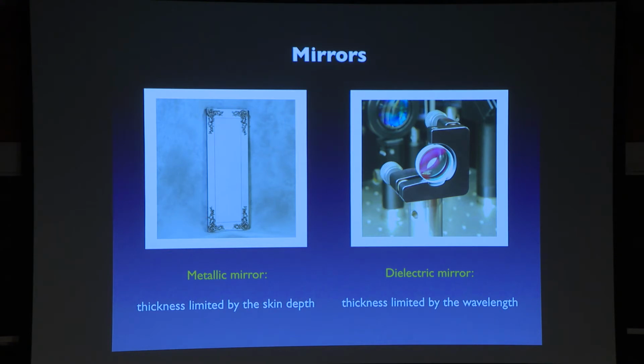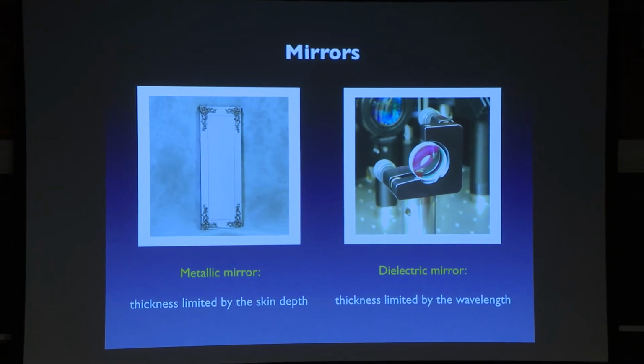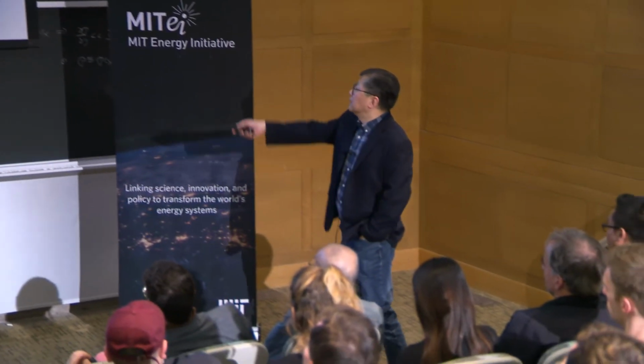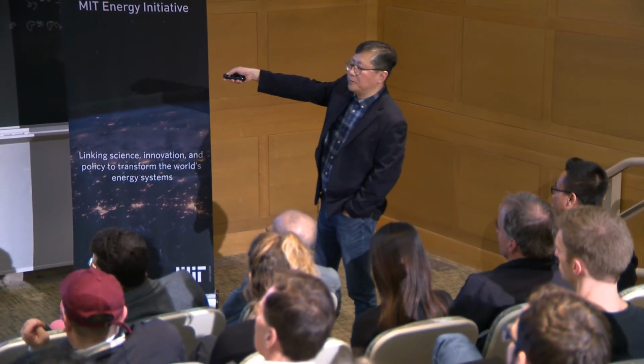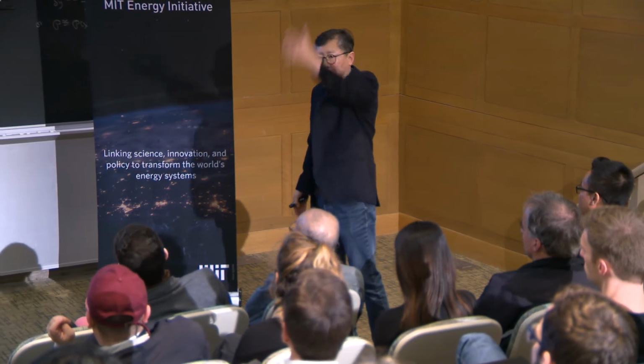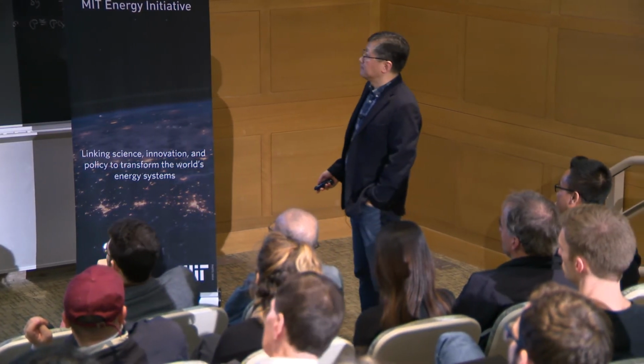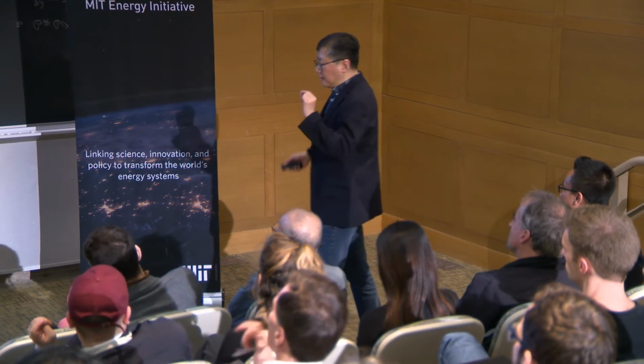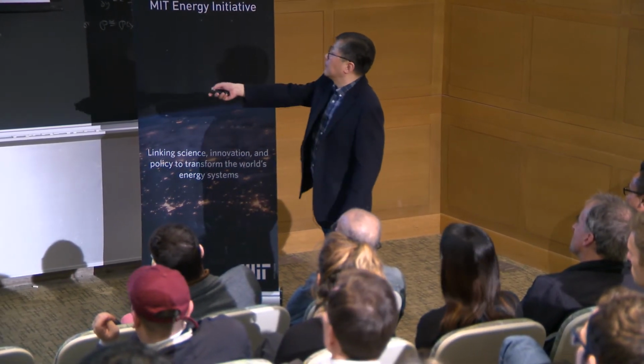So mirrors are ubiquitous everywhere. One of the things about mirrors that you often do not think about is the fact that mirrors should actually have finite thickness. Depending on the mechanism that you use to realize a mirror, whether it's a metallic mirror or a dielectric mirror, you actually have to have something like a micron thickness to get the proper reflective surface. So all the mirrors that you see have to have, say, something like a micron or larger length scale thickness. In the case of metallic mirrors, that thickness is limited by the skin depth of the metal. In the case of dielectric mirrors, the wavelength of the light determines the thickness.